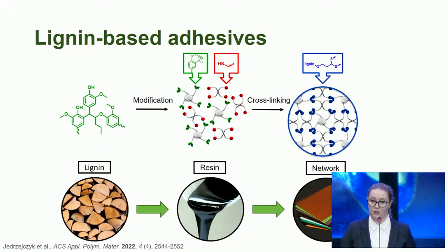Subsequently, I cross-linked the resins which were created, and I tested their performance as wood adhesives. It turned out that compared to phenol-formaldehyde resins, their performance was really good or even better, which makes this a very promising starting point, because phenol-formaldehyde resins are the main application of lignin in polymeric materials.